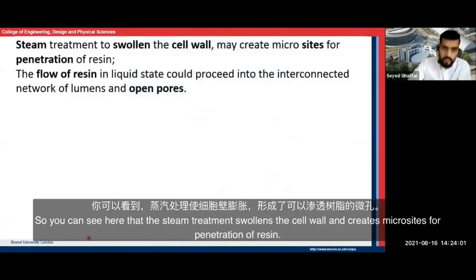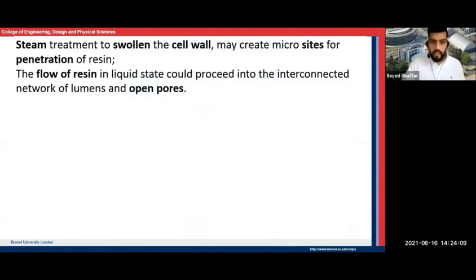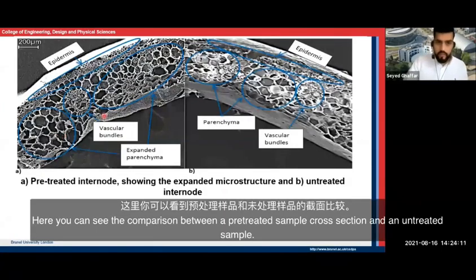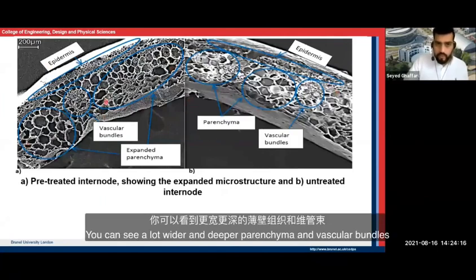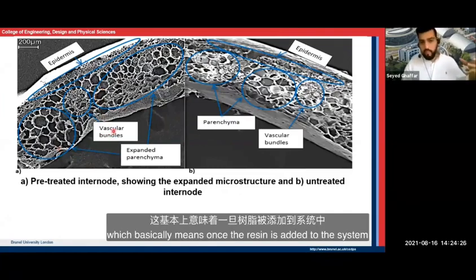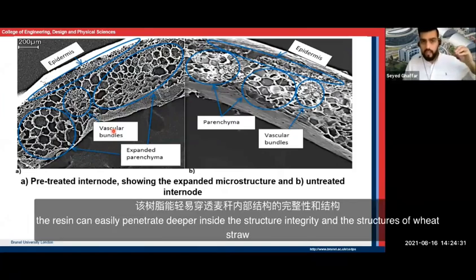So you can see here that the steam treatment swells the cell wall and creates microsites for penetration of resin. And here you can see the comparison between a pre-treated sample cross-section and an untreated sample. You can see a lot wider and deeper parenchyma and vascular bundles, which basically means once the resin is added to the system, the resin can easily penetrate deeper inside the structure integrity and the structures of wheat straw.